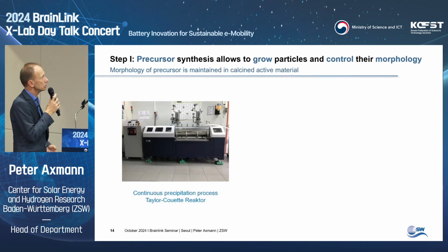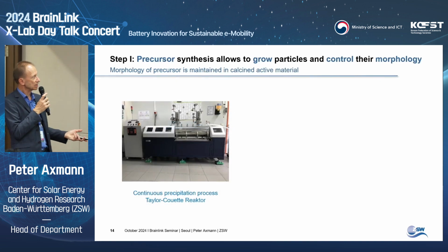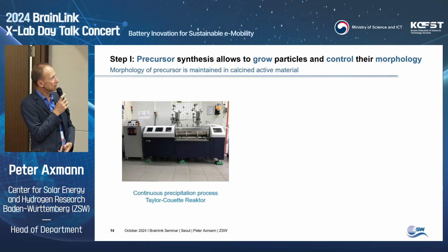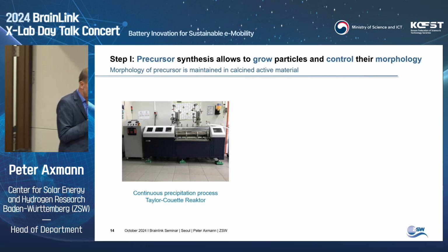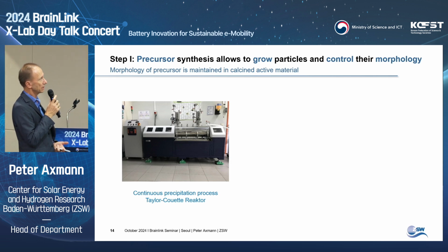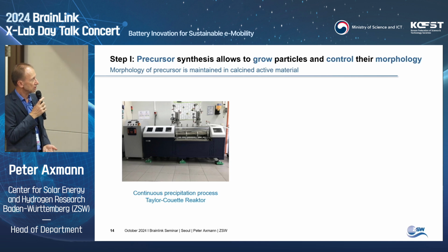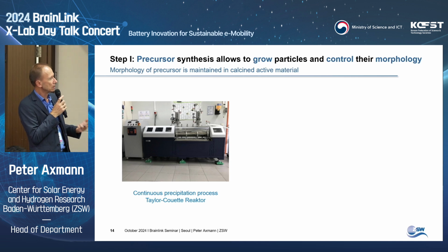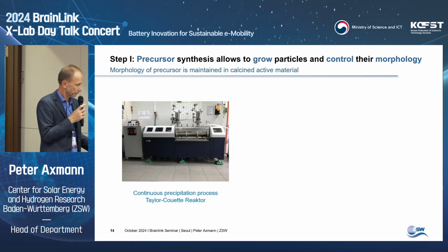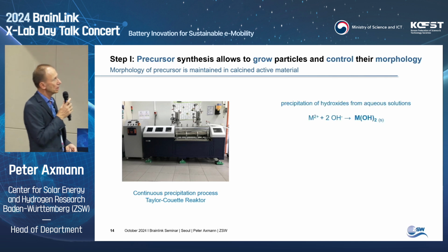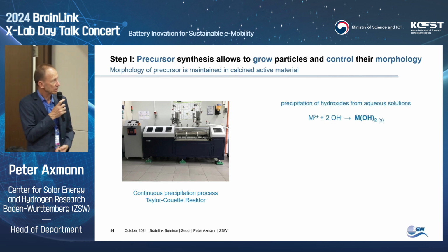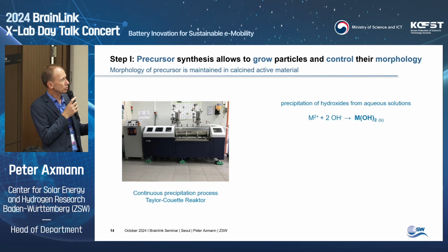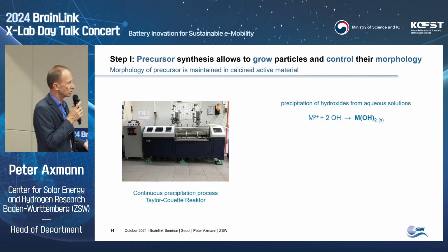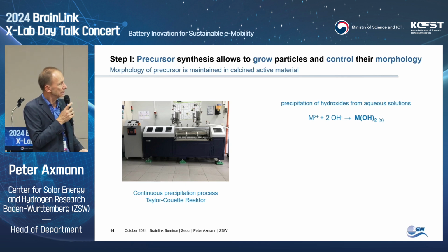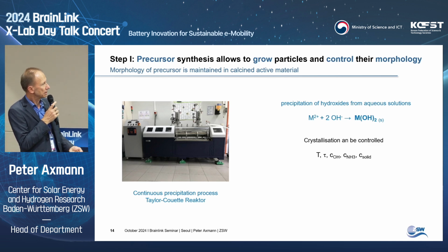And I will show here in the two steps what you can reach with the precursor synthesis and what can be changed later in the thermal treatment. So the precursor synthesis allows you to grow particles and to control their morphology, and this is done in continuously run precipitation reactors. The reaction equation is very easy. You precipitate the hydroxide just from the divalent metal with hydroxide, form a solid solution which you wash and dry and release, and get the powder then.